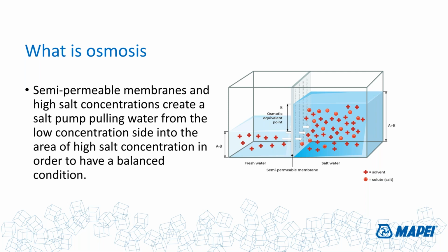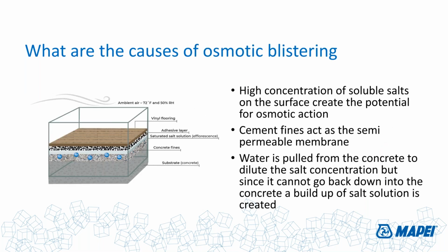On a concrete slab that's open, if you've got a high salt concentration on the surface, this process is working, but you're not seeing it because the water is coming up from the concrete slab, blending in with a high salt concentration, and then evaporating into the atmosphere. So you kind of have a built-in drying compound on the surface of the concrete slab that's working just fine on its own, pulling moisture out of the concrete, evaporating the outside, and leaving this high concentration of salt on the surface. Okay, that's what I would call that salt pump.